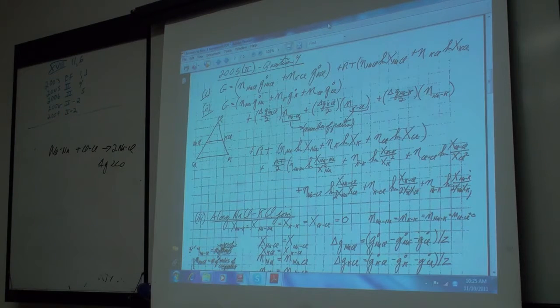This is just like an alloy model, a one sublattice alloy quasi-chemical model, plus the Gibbs energy of this pair reaction over 2 times the number of moles of sodium-chlorine pairs. This is just the quasi-chemical equations for a ternary one sublattice system, plus delta G of forming the KCl pairs, plus the delta G of forming the sodium-potassium pairs, multiplied by the number of pairs. That's your simple sublattice model.